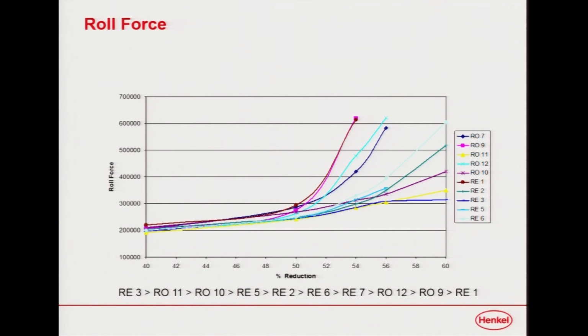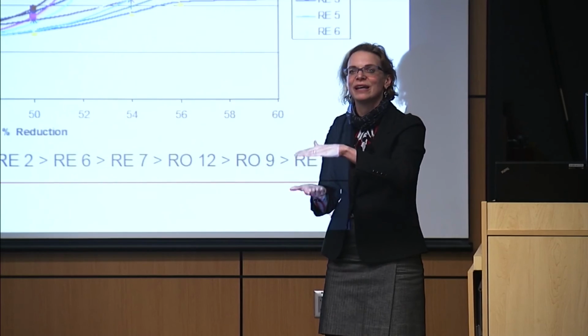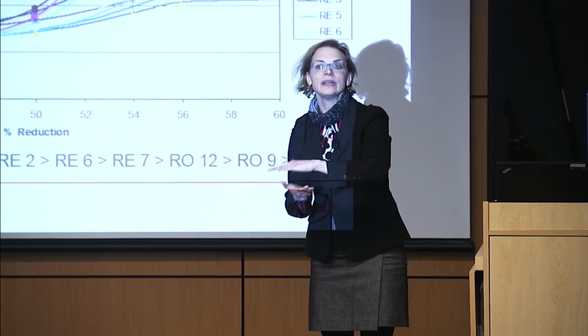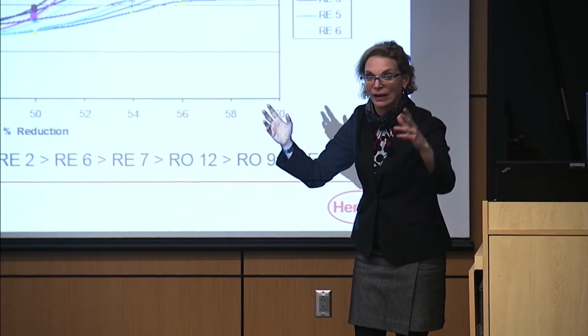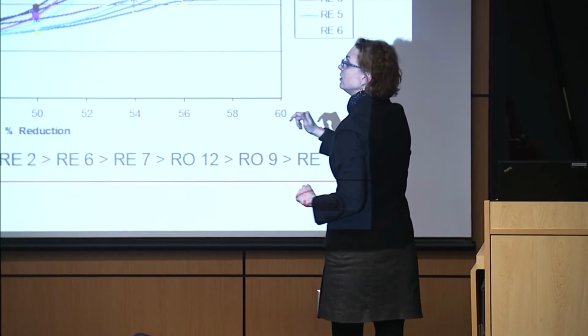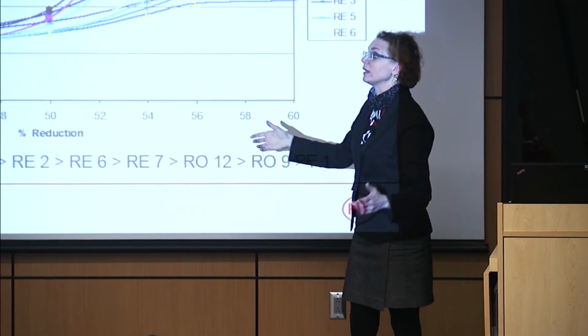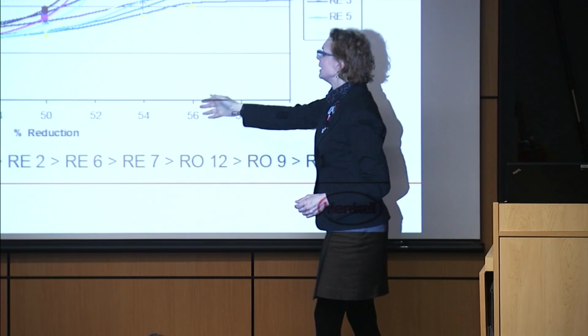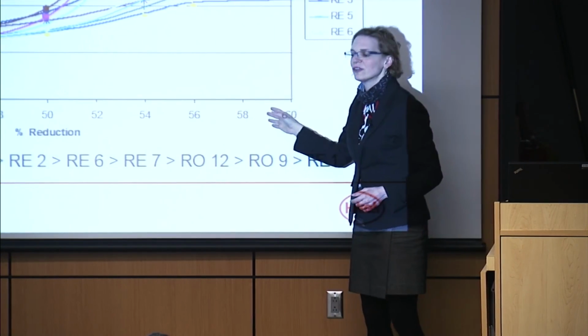Now, the roll force is very important, because that's the amount of pressure you're putting down, and eventually you can overcome the mechanical strength of the mill. So you really don't want to go there, because then your mill stands break, and that's expensive. Your work rolls fracture. Those are really expensive. So you want to be able to get out to these very, very high reduction ratios.